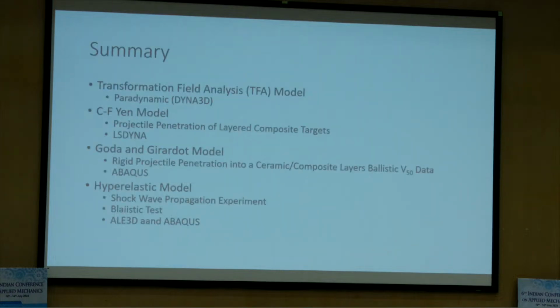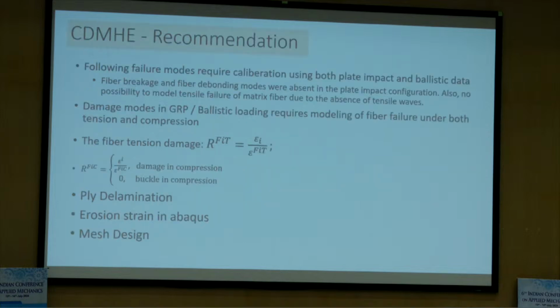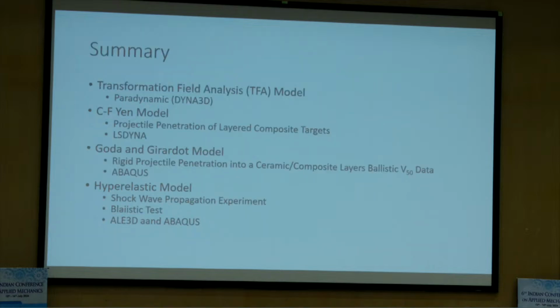Okay? So in summary, there's room for the model. The CDM hyperelasticity model can be improved. And actually the fiber parameters we did not touch. But when I go back, there's a PhD student working on it. We want to look at the fiber failure more closely to make sure that we can make predictions. And the mesh design is important, right? Your erosion strain can create problems. The ply delamination, the friction between the plies, all are still out there.